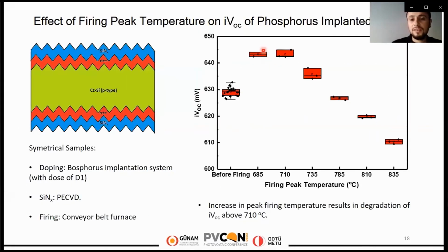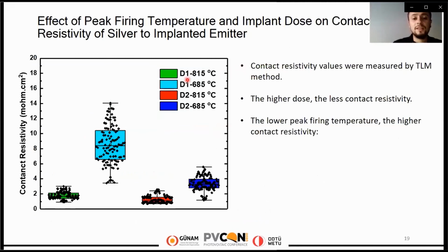For these firing temperatures, we also checked the contact resistivities. In the contact resistivity experiments, we applied 2 doses, D1 and D2, and also 2 firing temperatures. The contact resistivity measurements were conducted by the TLM method. The results show that the contact resistivity decreases with increasing firing temperature and increasing dose, as expected.